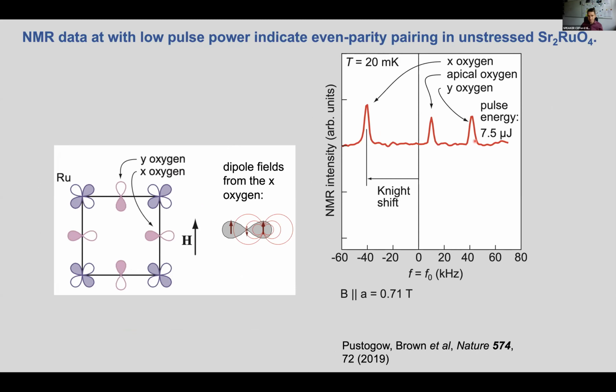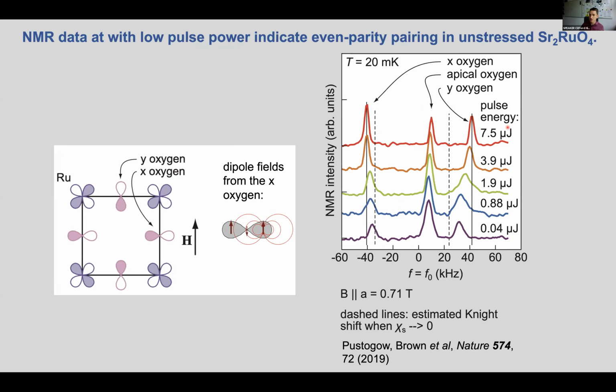And what Stuart Brown's group did is they then plotted this as a function of pulse energy. And what they saw is that as the pulse energy is reduced, the Knight shift is reduced. So their interpretation is that this high pulse energy is enough to heat up the electrons such that it is no longer superconducting. As they reduce the pulse energy, the electrons stay cold throughout the entire measurement, the sample stays superconducting, and they see a strong reduction in Knight shift. That is as expected for spin singlet pairing, where spin up must pair with spin down.